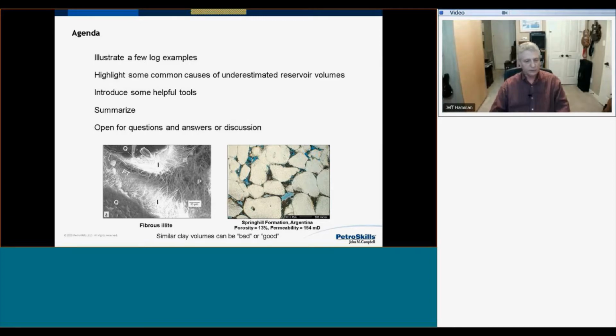I really like to have images. And these 2 images provide multiple purposes. One, they're an introduction to what this is all about, and they do provide really the crux of the information. And that is that in these 2 images, the one on the left is, do I have my laser pointer? Yes. This is an SEM image. The P stands for the pore, and the PT stands for the pore throat. And what we see is a fibrous illite that is going to destroy most of the permeability in that rock, and particularly when we coat all these surfaces with water and try and flow hydrocarbons, the effective permeability to hydrocarbons will be negligible. So that is when clay is bad.